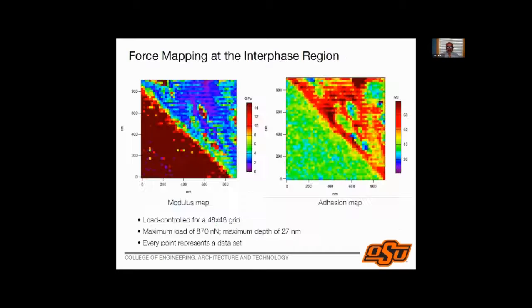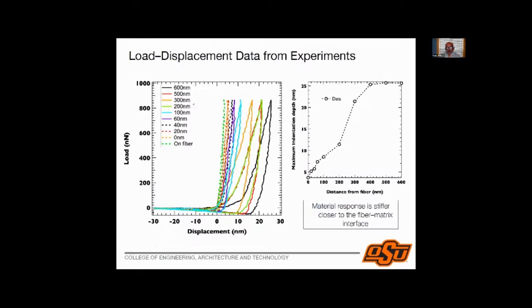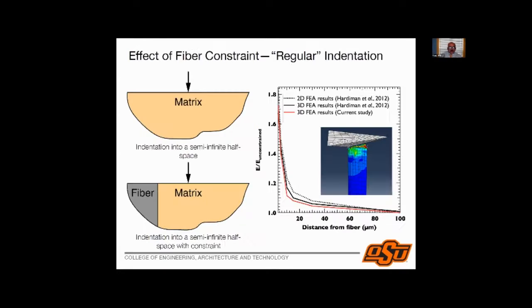That means that this region over here, my interface region, has a modulus that is higher than the rest of the bulk epoxy. So this is very interesting, because this is one of the first measurements which shows that the interface region has a higher modulus. How much higher? Let's try and figure that out right now.